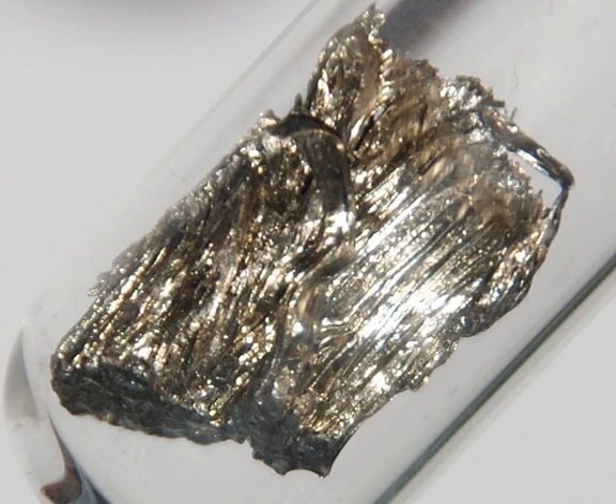degrees Celsius. All these materials are hard, brittle, dark gray solids with the hardness increasing with the boron content. Samarium diboride is too volatile to be produced with these methods and requires high pressure, about 65 kilobars, and low temperatures between 1140 and 1240 degrees Celsius to stabilize its growth. Increasing the temperature results in the preferential formation of SmB6.